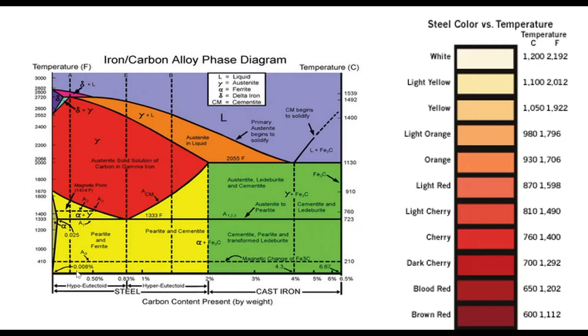If I get it hot and I go up into this red area, this crystal structure, which is body-centered cubic, changes into face-centered cubic. Body-centered cubic is ferrite. Face-centered cubic is austenite. When I get up to this temperature, then I can dissolve over 1% carbon. So the trick in heat treatment of ordinary steels is I get it hot enough to dissolve all of the carbon.